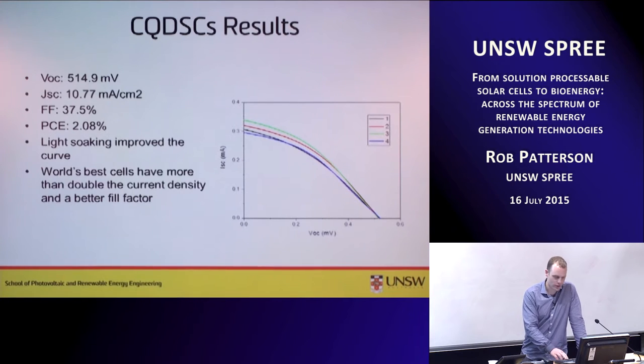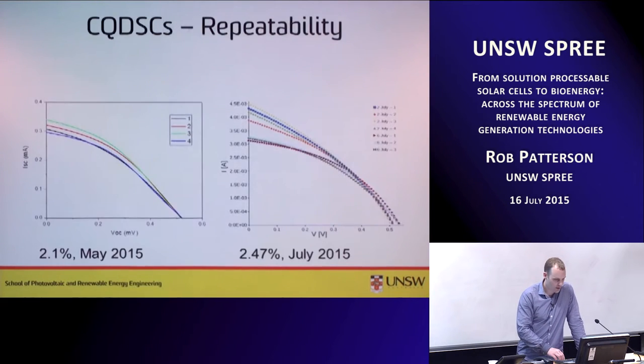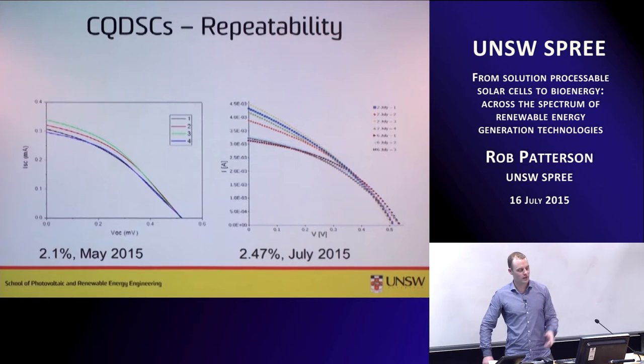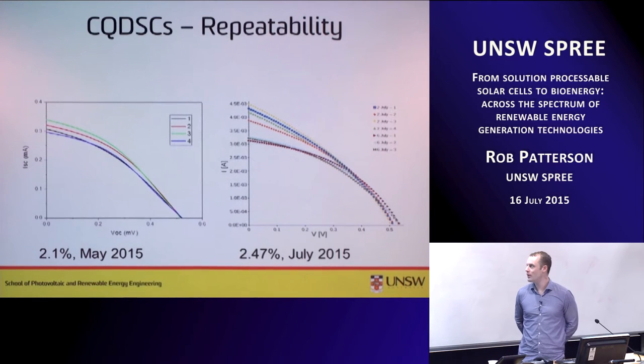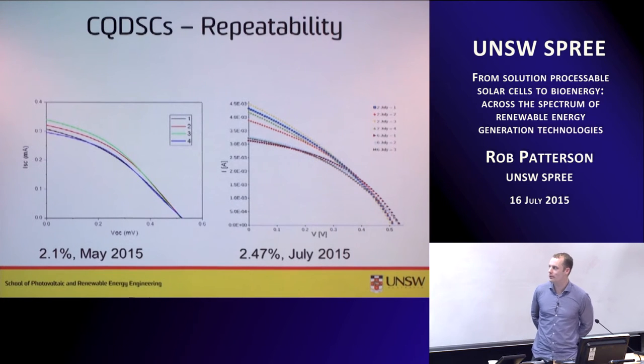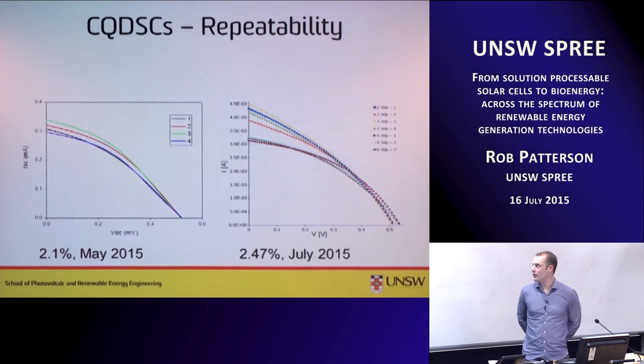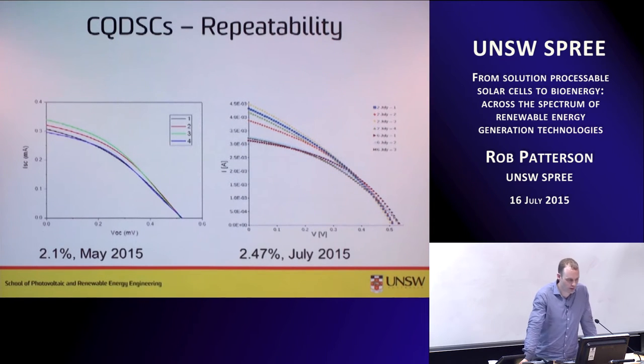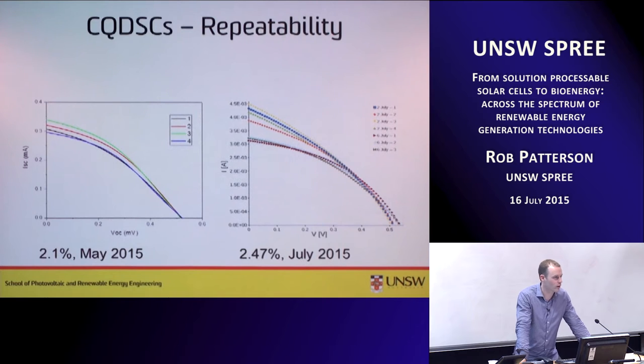And you might ask, is this just your best cell? Did you get lucky? No, in this cell type, we've been able to reproduce this result. In May, when that cell was made, we were at about 2.1%, and now we've climbed up about a half a percent, or 0.4%, onto the next one. You can see that there are many places on each cell where the efficiency is measurable. So these are working cells. We'd like for them to approach this 9.9% world record efficiency clearly, and we're getting there. So we're doing our best to get further.